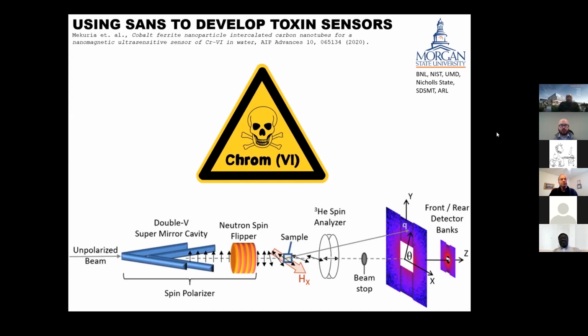And the VSANS instrument is able to help probe the structure of the intercalated magnetic nanoparticles, both with and without the chromium, when it's placed in a magnetic field. And since they were interested in the magnetic structure of the nanoparticles, they used polarized neutrons to separate the magnetic scattering from the structural. And that's one of these other key killer applications of neutrons: we can actually disentangle the structure of a material from its magnetic structure.